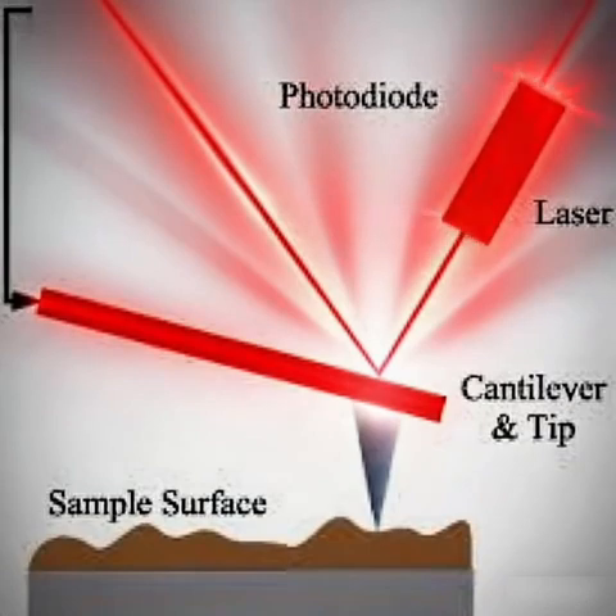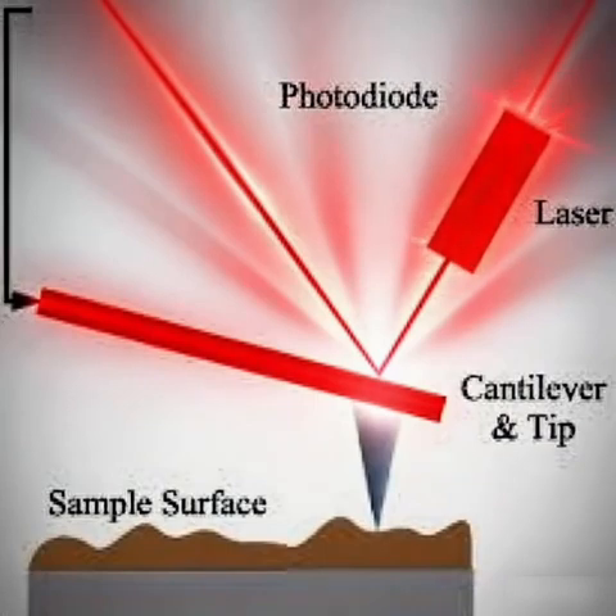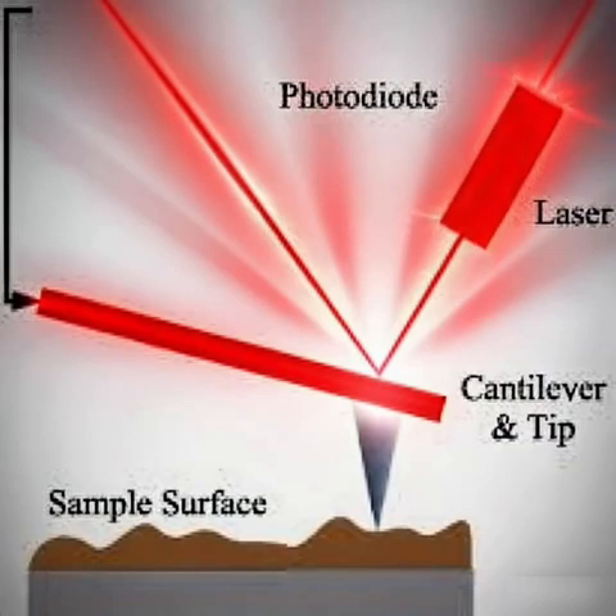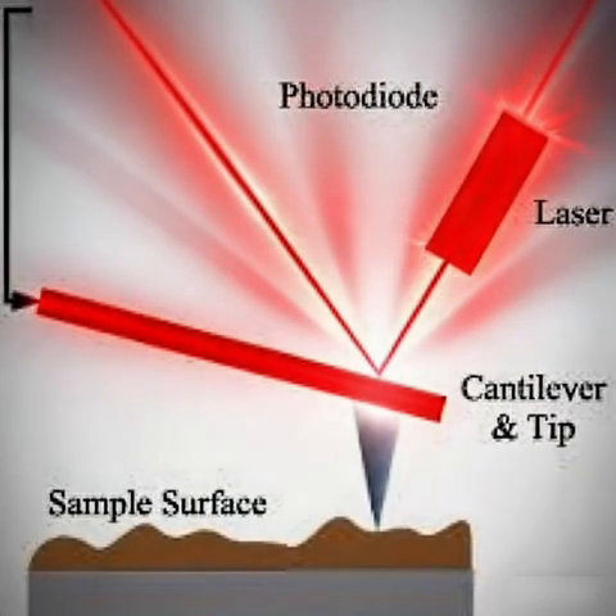Right. That brings us to nano-TDDB. That stands for time-dependent dielectric breakdown. This is a direct reliability test. It really stresses the material. The idea here is you apply a gradually increasing voltage, a bias, using an AFM conductive probe, and you watch precisely when the insulating layer fails, the breakdown voltage, and how long it takes. This is just immensely valuable for testing the local strength of really critical components like the gate oxides in transistors or those low-k dielectric materials used for insulation. It can detect tiny, tiny pinholes or weaknesses in the dielectric that might otherwise just slip through.